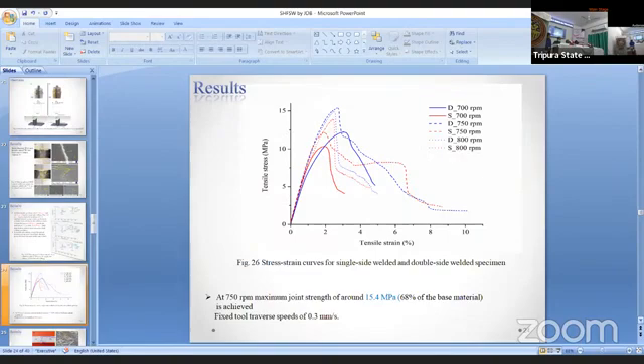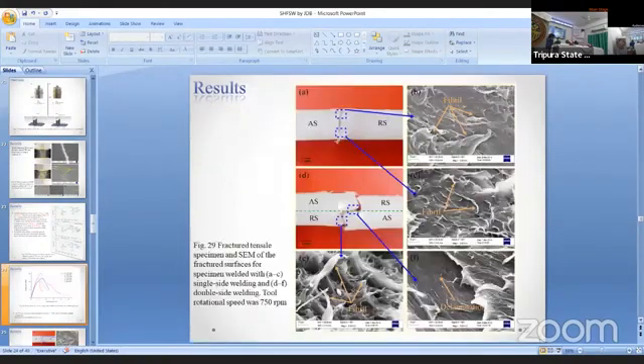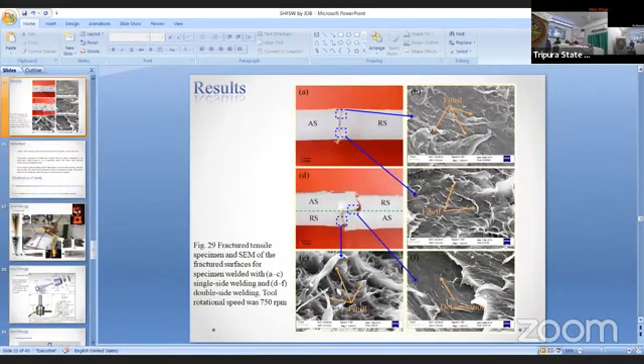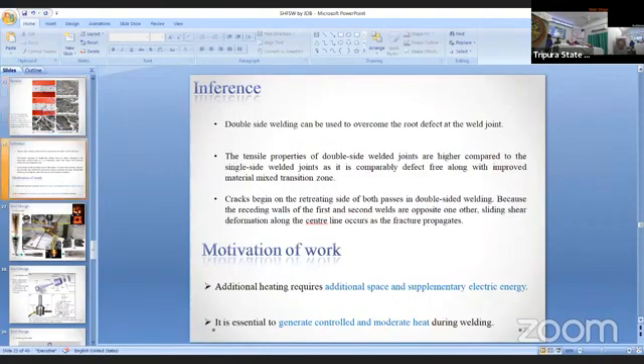Here we can see that D stands for double-sided and S stands for single-sided. At different RPMs, we could achieve a better strength of the joint. But again, we thought of improving the quality of the joint. That's why we thought of developing another tool, which is a self-heated tool. From the fractured tensile specimens and some of the fracture surfaces, we can see that after the tensile test, fibrillary structures are present, which indicates a ductile mode of failure.